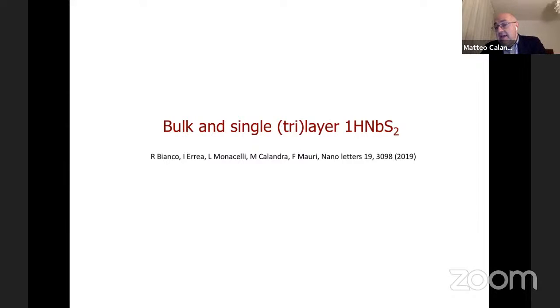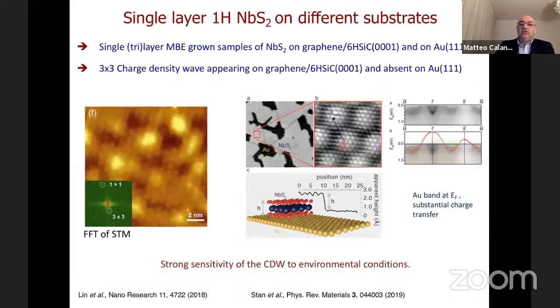However, as I showed you in my previous two examples, anharmonicity is very important, and what I believed was true in 2012 turned out not to be complete. And this is dramatically true in single layer and bulk niobium disulfide. So the bulk, 1H, I say the bulk to say that is one layer, the single layer, sorry, 1H is one layer. So the bulk 2H niobium disulfide has no charge density wave.